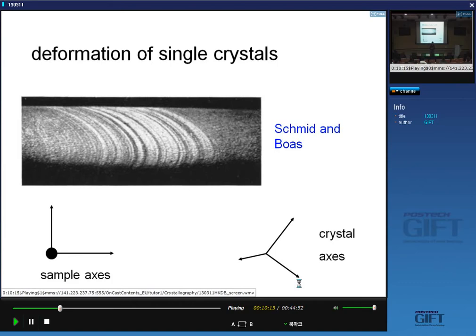Now, slip operates by shear, doesn't it? Yeah. Slip means shear. So even though you're applying a tensile stress, that tensile stress will operate through the shear stress that you put on any different slip plane, right? So you've got to resolve that tensile stress as a shear stress on the slip plane. And that plane which will have the greatest shear stress in the slip direction will be the one which operates first. And we'll come to this later, but they were the first people to derive the law which predicts which slip system has the largest shear stress in the shear direction, and that's known as the Schmid factor after Schmid and Boas. So here is a single crystal, and you can see that it's slipping on a particular set of planes. So I can represent all the slip systems on a stereogram, and I can put the tensile axis on the stereogram, and therefore I can discover which slip system is going to operate first. Okay? So I'm not teaching you how to do that as yet, but we will come to that later.